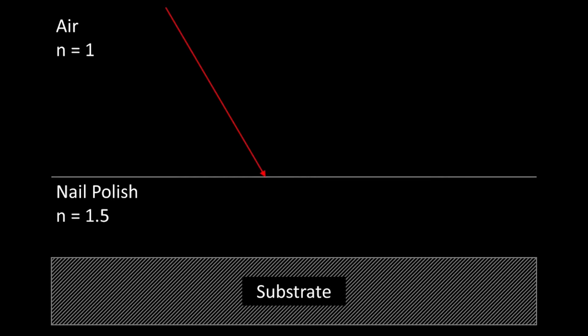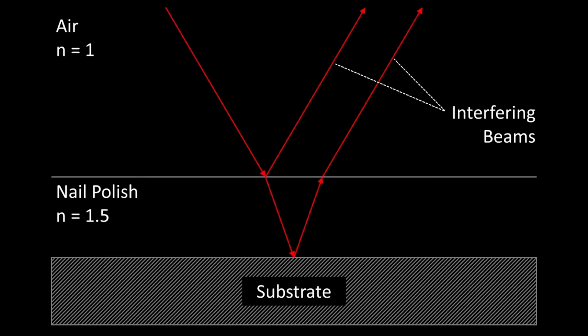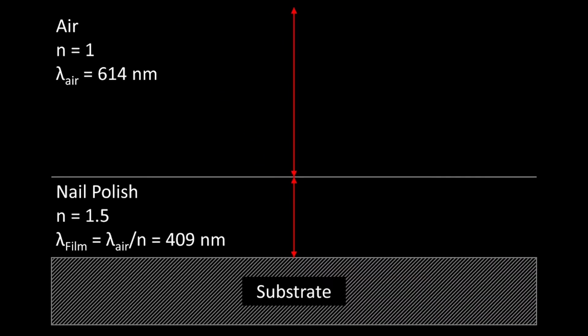This is caused by light interfering with itself, and we can use this to get a real measurement of the film's thickness. Some of the light reflects off the top of the film, and some enters the film to reflect off the bottom. These beams interfere with each other to create the alternating light and dark stripes, or fringes. The wavelength of the red light here is 614 nanometers in air, and shortens to 409 nanometers in the film because of the difference of refractive index. The bright spots occur when an integer number of wavelengths fit within the film. When illuminated and observed from directly above, the film's thickness can be calculated as the wavelength divided by 2.